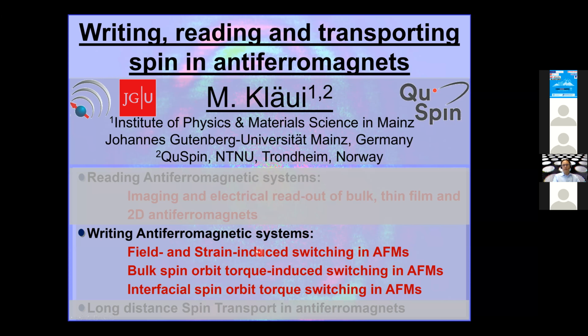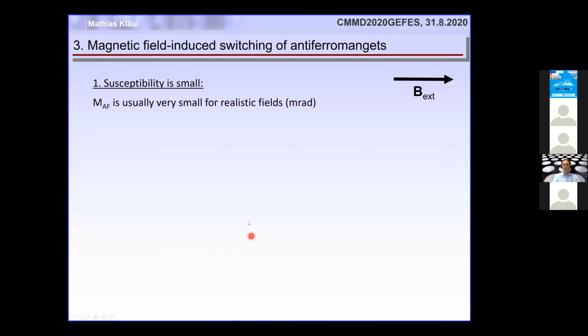Okay, so now let's come to the writing. For the writing, we start with the simplest thing, which is fields. I already told you that if you apply a magnetic field, the two sublattices will cant very little because this magnetic field is usually much smaller than the exchange interaction between the two sublattices. So here this is highly exaggerated, that the two sublattices cant a little bit along the field direction. Usually this is very, very small.